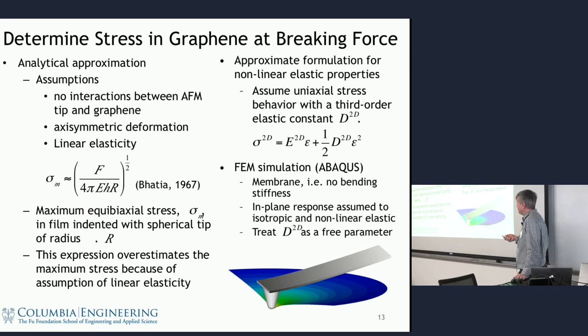So in this case, this is a great example of that. You can look up in a book and find a formula for the maximum stress on a membrane as a function of force applied and the radius of curvature of the indenter tip. The problem is, this is based on linear mechanics. It's based on assuming that the material is in the linear stress strain state. But if you do a finite element simulation and look at the magnitude of the strain underneath this tip, it's certainly 10%, 20%. It's incredibly high. And once you see strains like that, you know you're not in the linear regime anymore. You have to think about the nonlinear behavior of the material.